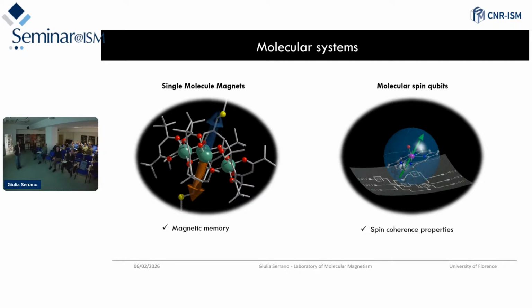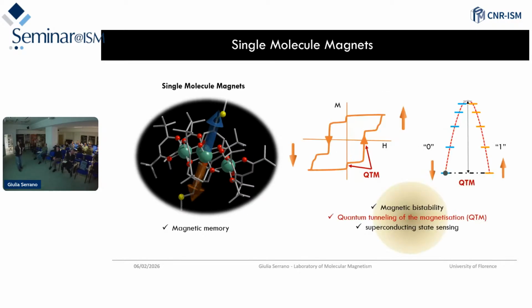So, sticking to single molecule magnets, these are tiny molecules, one molecule is more or less 1 nanometer large, that hold a magnetic hysteresis loop in a single molecule. It's like a small magnet that doesn't need magnetic domains, as in normal magnets. So it is usually formed by a magnetic core embedding some transition metal ions or lanthanide ions, having a spin, usually a large spin number, and a strong magnetic anisotropy.